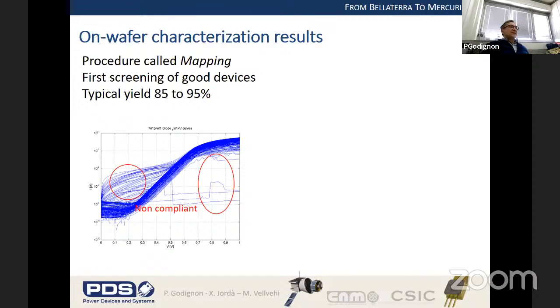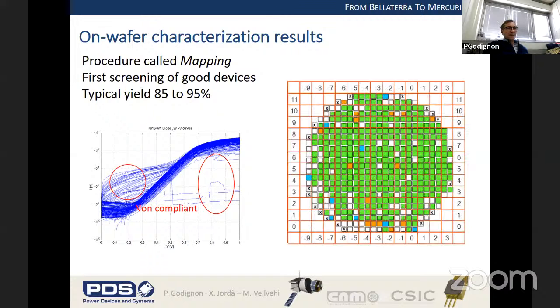So an ideal yield, a good yield, would be between 85 and 95% of good devices on the wafer. You have, for example, the forward characteristic of all the devices of a full wafer, and you can see that there is a group of standard characteristics, and some of the characteristics are out of specs. So definitively, this device will not be compliant for further processing.